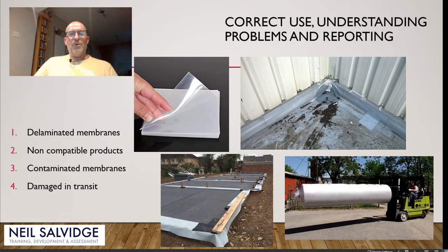So just back on that, and we've also got contaminated membrane. So we might be looking at products where somebody's tried to fuse them or tape them and they've not been cleaned, or they've got debris on them. If you leave a membrane over a period of time, it could possibly give you a problem, where it's exposed to UV light, moisture exposure. It's quite a serious problem, and you'll find when you come to weld that often welding or heat fusing will fail at this point, because the contaminants will hinder that process. So just be mindful of that.